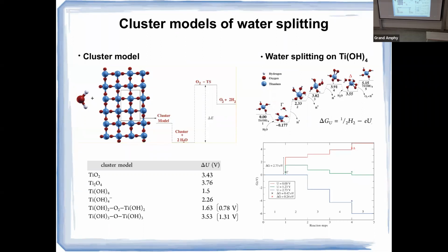So we treat, for example, adding hydrogen atoms to saturate the bonds, and then you see that it goes down to 1/2 of the previous models that have been used, the cluster model. Even for the simpler one, we consider dimeric models. I won't spend too much time here. I just want to tell you that it still is not quantitative, but for example, with relatively small clusters, you can already predict the outperforming of the rutile variant with respect to the anatase variant of the titanium dioxide. So you can get the same trends like in the experiment, although you cannot reproduce the numbers.